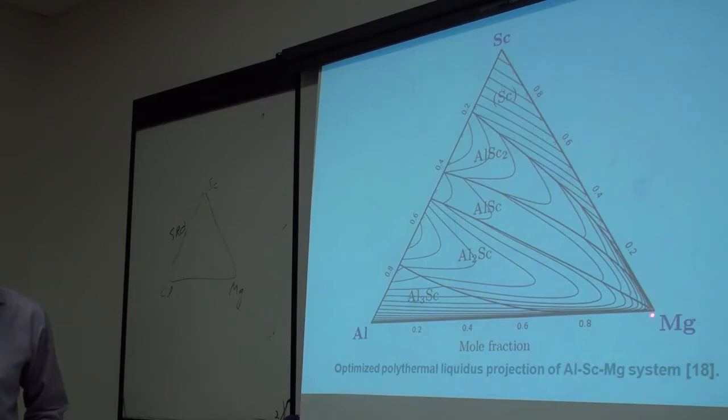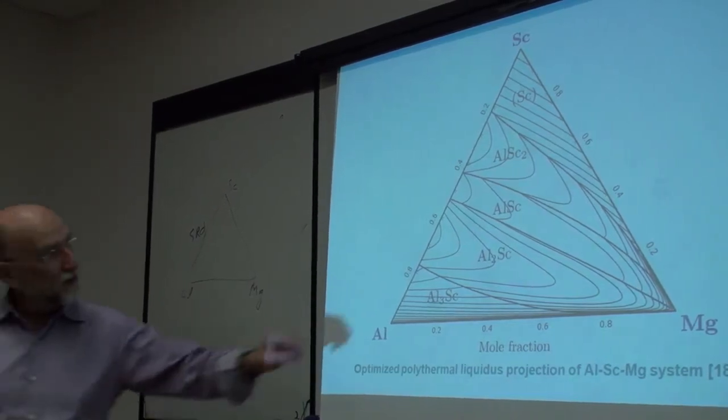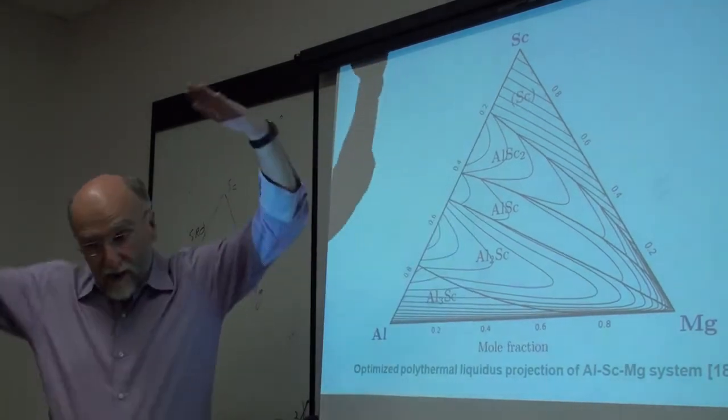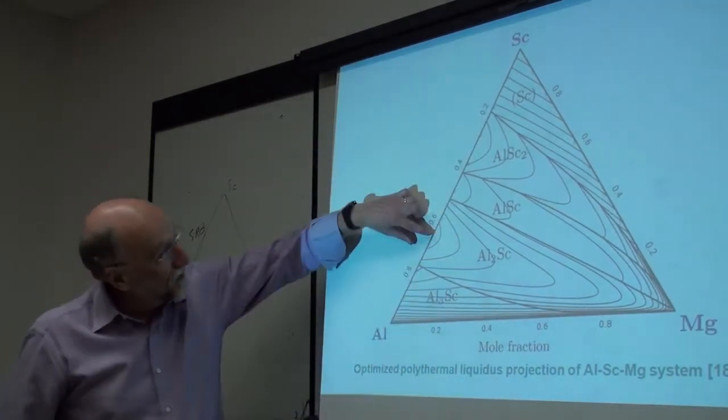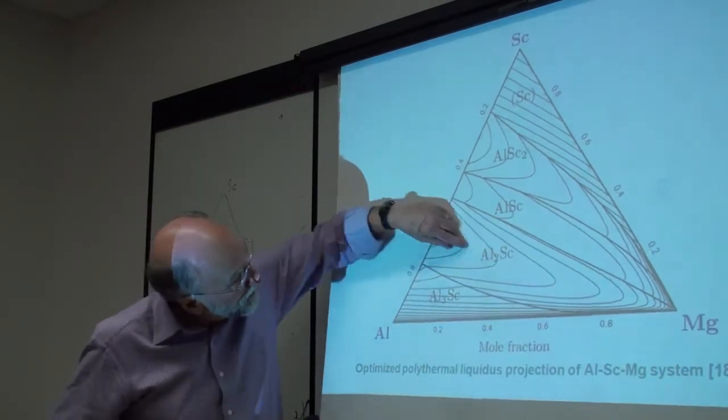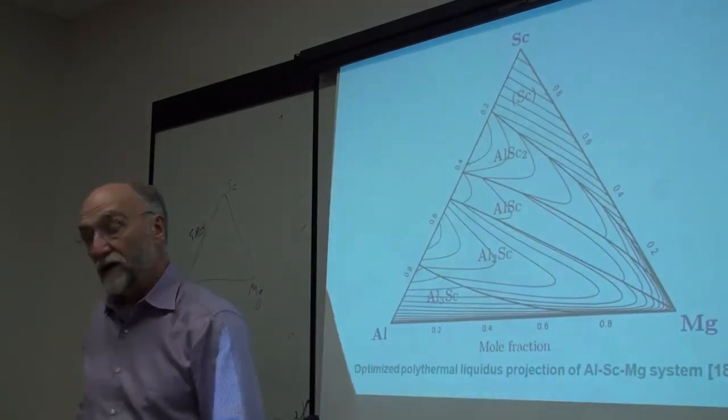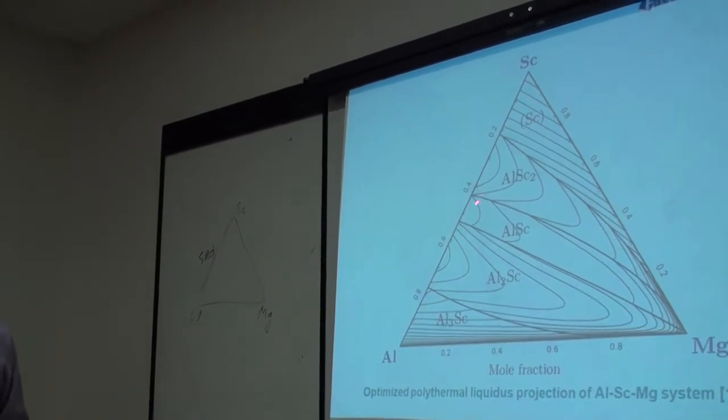If we treated this system here in the liquid phase as an ideal solution, these isotherms would be much closer together, and the Liquidus would be much, much lower. If you started here and went across this way, you'd be descending in temperature much, much more quickly. So this is very typical. Again, this seems a little bit backwards. Here you've got aluminum-scandium, with very negative deviations forming the nearest neighbors, short-range ordering, and yet this gives you positive deviations, aiming from this corner up towards the ordered side.